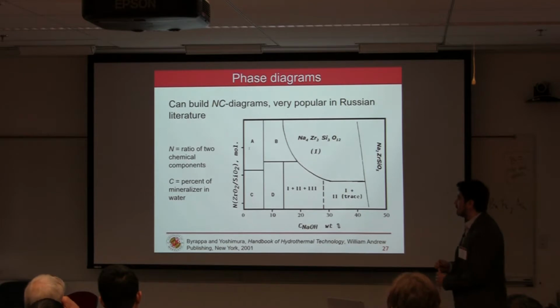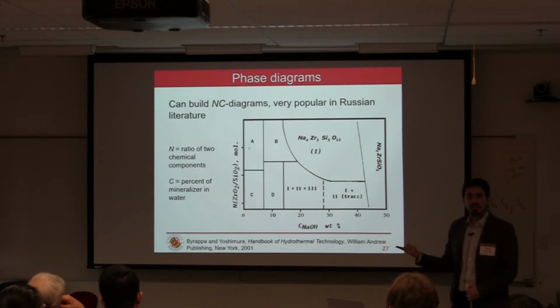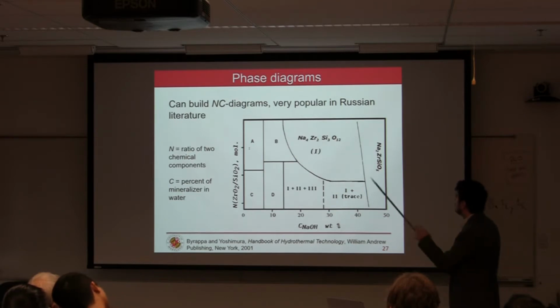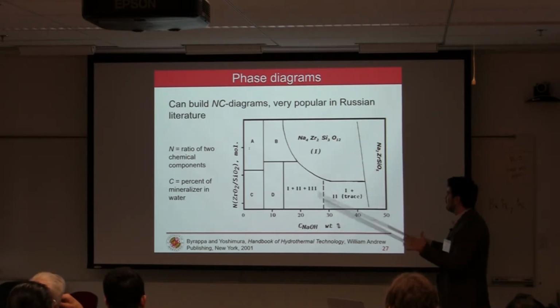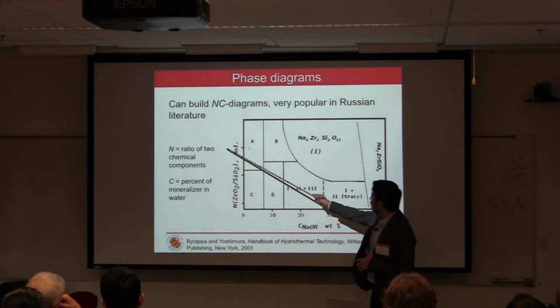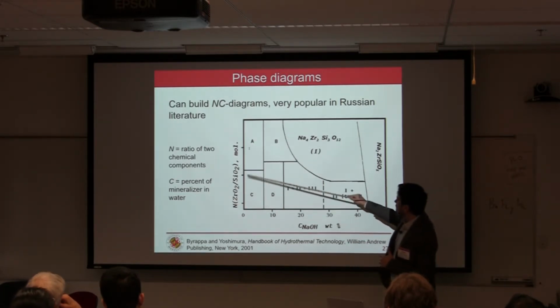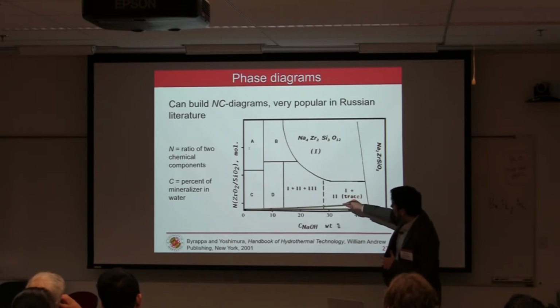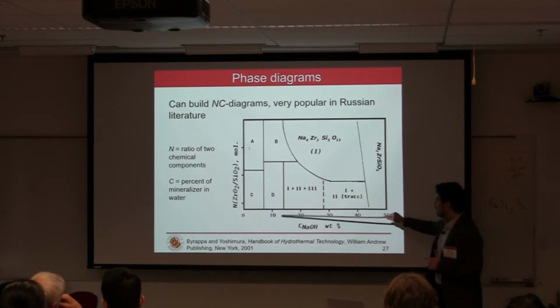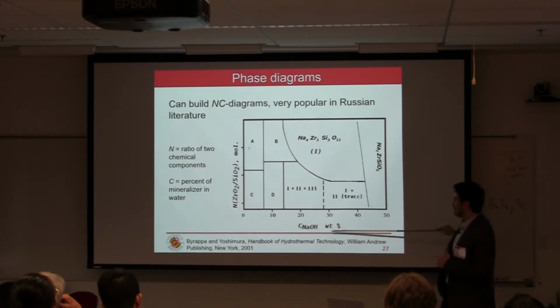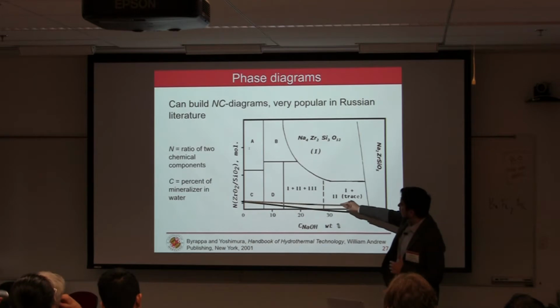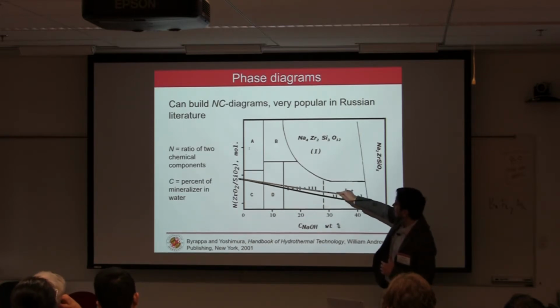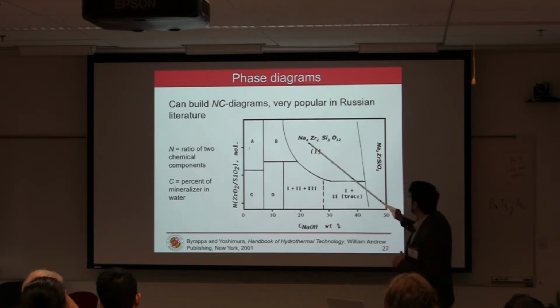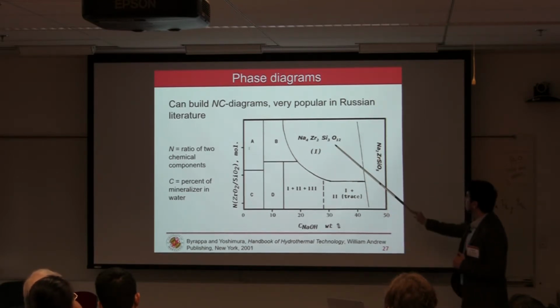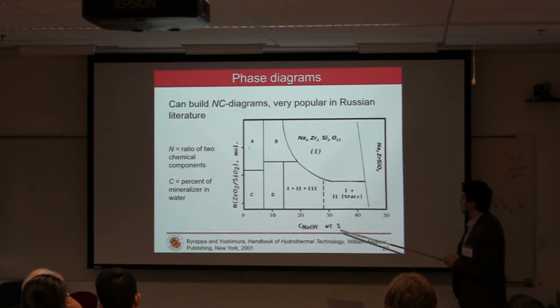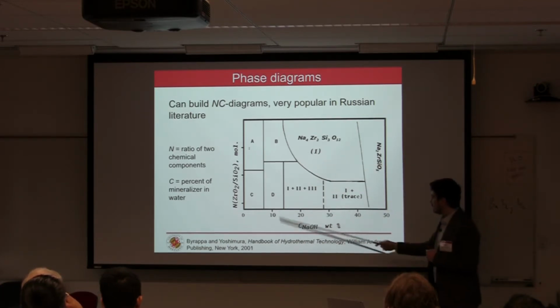Oh, before I get to that, let me just say that there were other phase diagrams that were popular in the literature back then. These were very popular in the Russian literature, actually, I guess during the Cold War when both sides weren't really speaking. What they were doing was different from a lot of Western phase diagrams, which was to have the concentration of sodium hydroxide. They called this the mineralizer. So this was just changing the pH of the solution versus a ratio of two oxides. For example, this was zirconium oxide versus silica, and they were getting various types of phases and mixtures of phases as well. And so these are also very useful if you can find them.